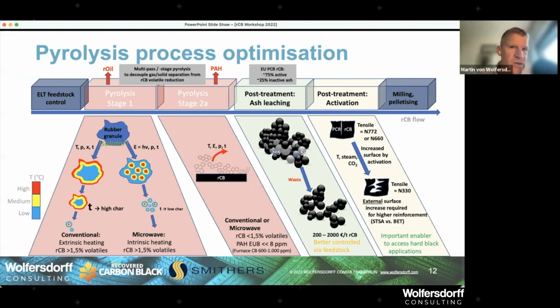We can also do a dry granulation if that is your question, but typically the dry granulation is producing pellets that are much harder. And then again, if you go in the rubber mixing process and the pellets are too hard, they're not broken up, and everything that is not dispersed in the rubber cannot do the reinforcement work in the rubber. And then we have problems again. So wet granulation is important.